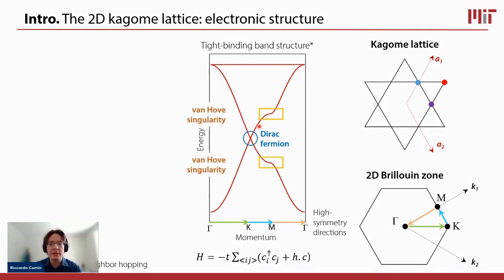And we have these regions where the band dispersion gets locally flat. So the band rises and then stops and then continues to rise in energy. And here is the same. So the band rises from the gamma point, and then it stops just for a little bit around this M point here, and then it continues. And then the third prominent feature of this band structure is the flat band at the top. So there's a completely flat band where all the electrons have exactly the same energy.